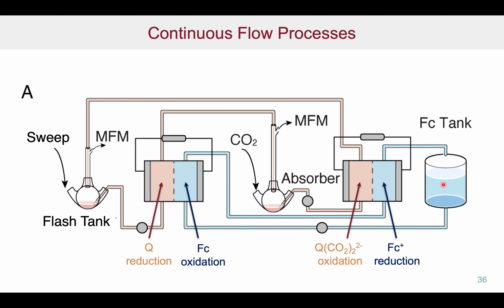This can also be done in a continuous process if we wish. In this particular case, we have an electrochemical cell in which the quinone solution flows through here, with a ferrocene solution, and we can do the oxidation of the ferrocene and the reduction of the quinone. The reduced quinone can then be taken to the absorber. We pick up the CO2, and then it can go to a desorption unit. We do the oxidation of the compound and a reduction of the ferrocenium, as shown here in this cell, and then we can disengage the CO2 that's released in a sweep stream. The ferrocene just goes around in this loop as a working fluid.